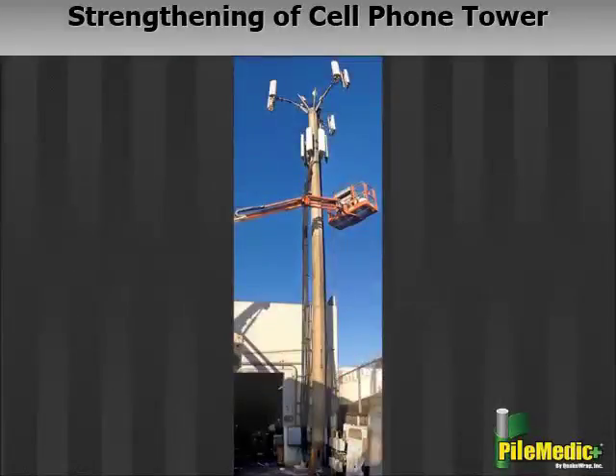The particular tower shown in this video is a monopole structure located in a high seismic zone in Southern California. It is nearly 55 feet, or 17 meters, tall. The tower is made of a hollow-spun precast concrete tube with a thickness of less than 2 inches or 50 millimeters. Our analysis indicated that the entire tower height required tension reinforcement. In addition, the concrete wall for the lower half of the tower was too thin, requiring a thicker concrete to resist the load safely.